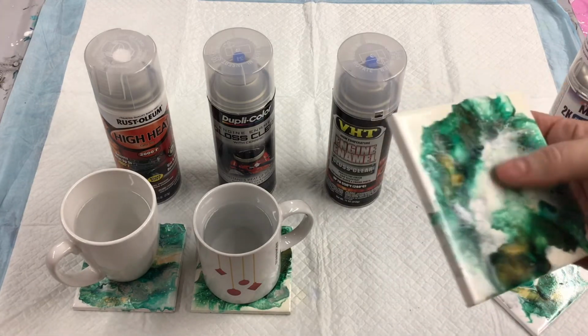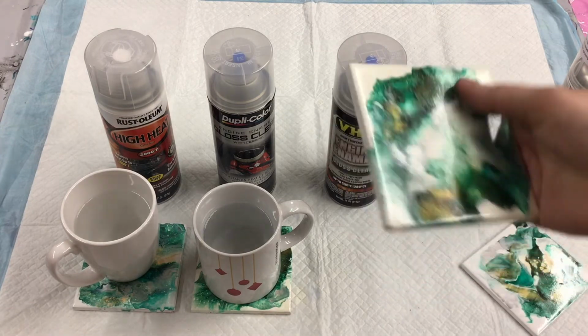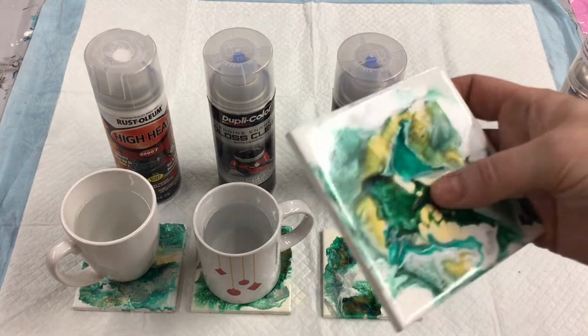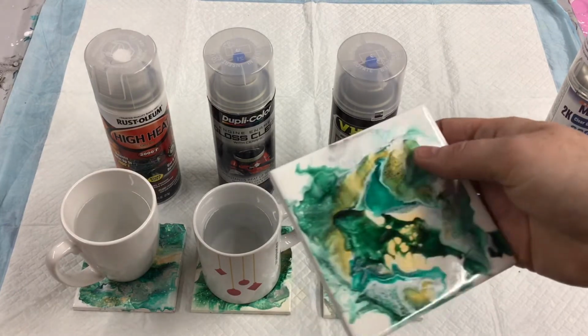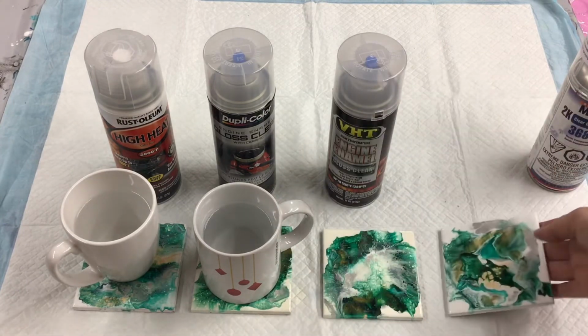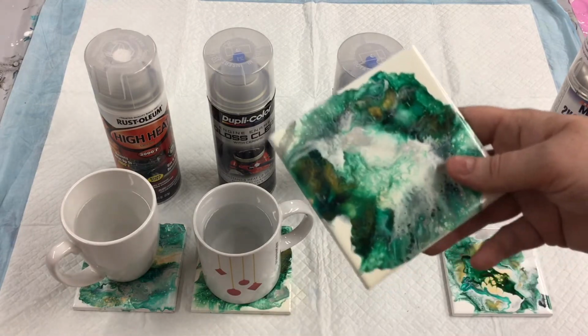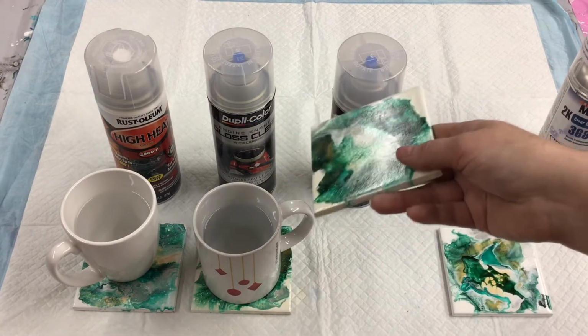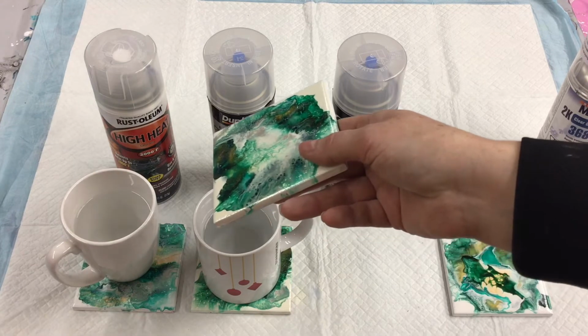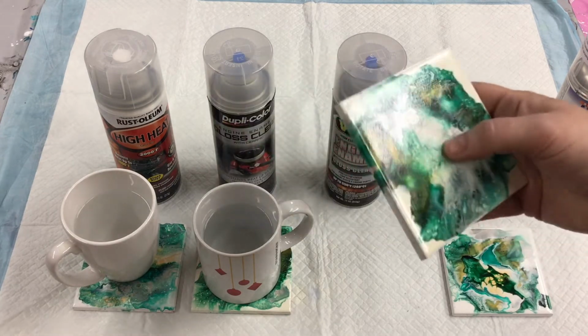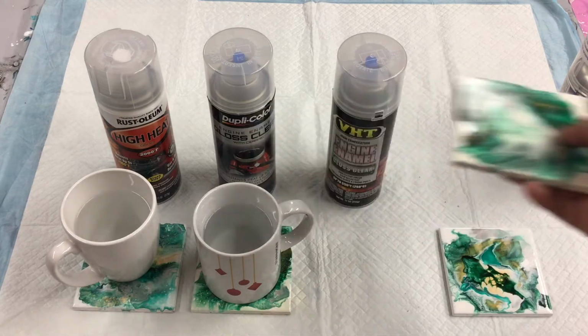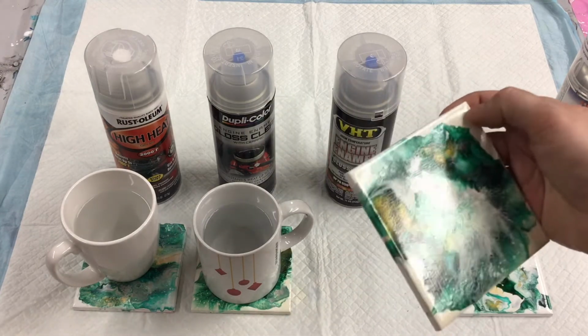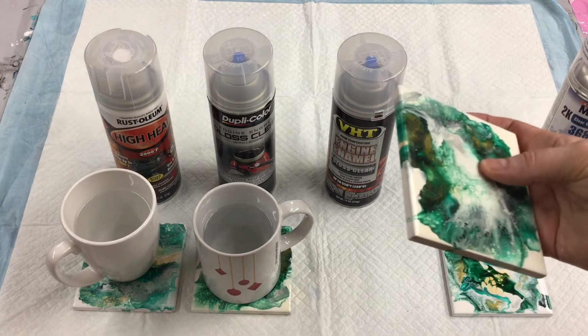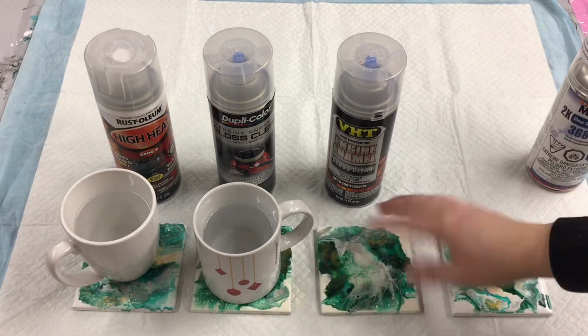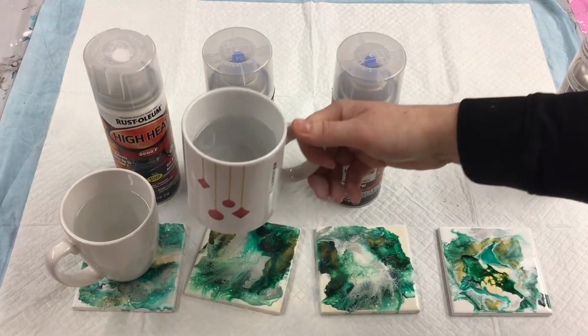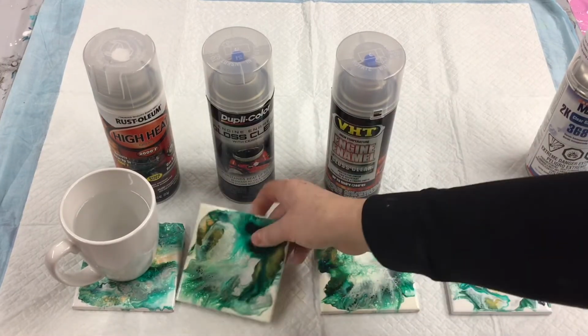It doesn't have the same glossiness. I feel like it's a little bit thinner and not quite as glossy as the 2K. The 2K, by the way, if I didn't mention, this one was $20 on Amazon. VHT was, I believe, $12. Duplicolor was $9. Rust-Oleum High Heat I got for just about $10. So these are all about half the cost of that one. But this actually is holding up pretty well, except for that little bit of yellowing. A little bit of stick on the Duplicolor.